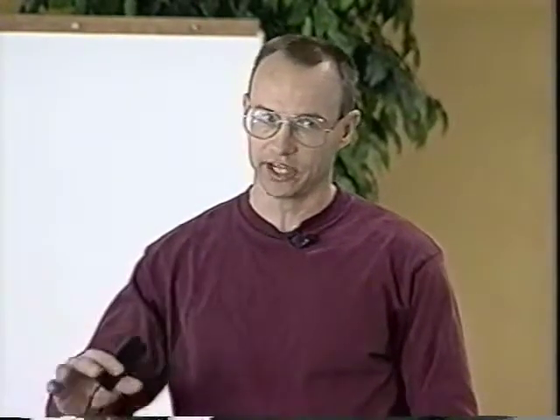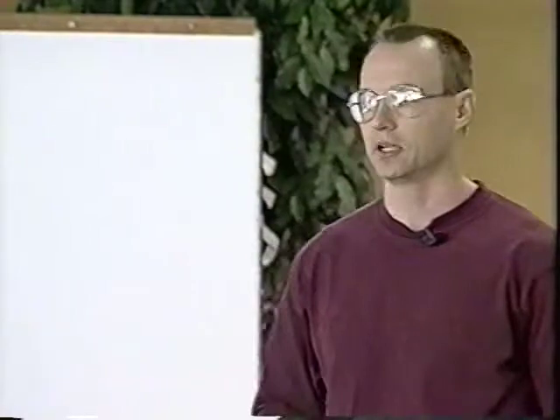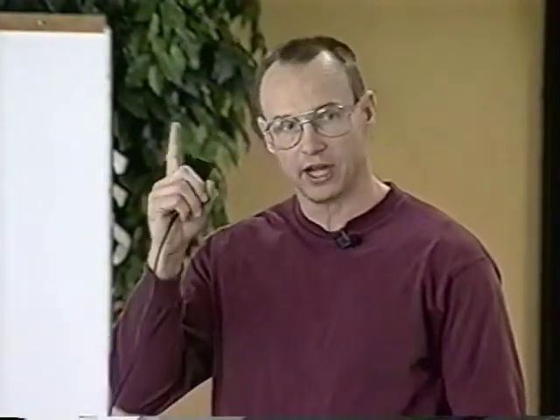And then if we miss the chemistry here, we're pretty well locked in. When we get into the ladle, if we're low, we can always add a little bit more, but if we're high, we can't take it back out. So we're kind of locked into the chemistry that we get at tap here. And if we miss that, sometimes we'll call you up on the phone and we'll beg you guys to take it as is. And a lot of times you do, but sometimes you don't. And now we got 300 tons of stock sitting out there that we got to find a home for, and we got to go back in and remake your heat. And we do that on average about once a day. That's the chemistry.